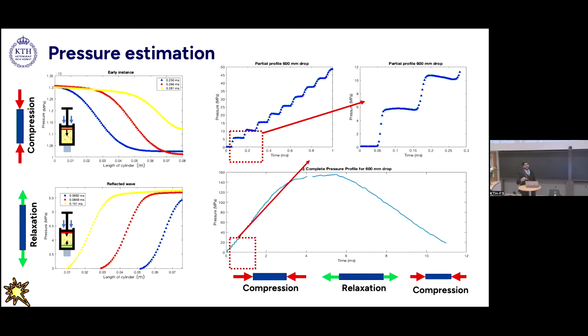And also from the literature, we know that every shock wave has a shear wave associated with it. So the particle goes through compression, relaxation, compression, and shear forces all the way along the line. And that's exactly causing the fiber breakage. That's the bottom line for this.